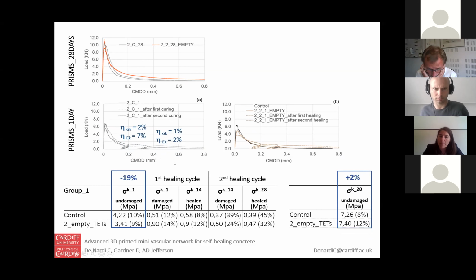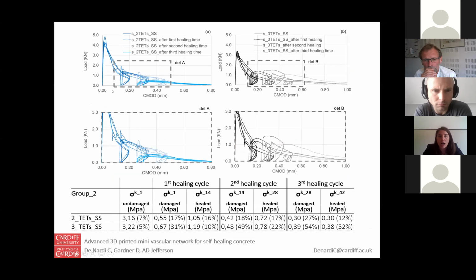Then we did 3 damage healing cycles. Here you can see just 2 because we didn't have any healing after the second one. So for control samples, after the first and second damage healing cycles, the healing efficacy is almost negligible, and it is almost worse when the samples contained 2 empty TETs. Here you can see samples containing 2 TETs and 3 TETs, respectively on the left and on the right.